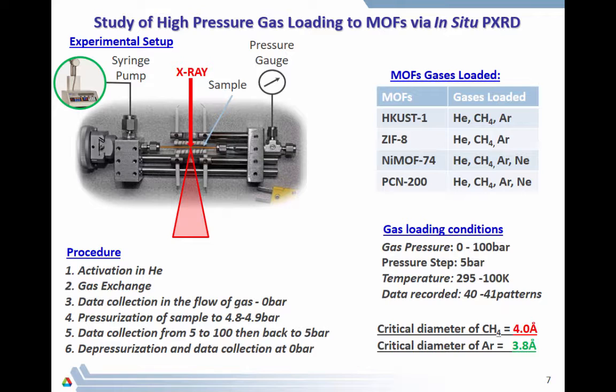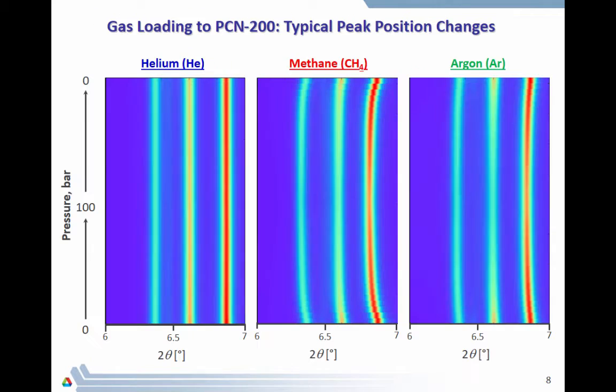For example, we can study the metal organic frameworks under different pressures of gases. And as I told you, we can take our flow cell, block one end of it, put the pressure gauge there, and connect the other end to the syringe pump with a gas of interest, and the syringe pump would change the pressure inside the cell. You could observe it on a gauge, and during the entire time while you do it, you shoot X-rays on your material and collect diffraction data from it. What is really great, this can be easily combined with a cryostream system. Therefore, you will be able to measure how the structure of a material changes from both temperature and pressure at the same time.